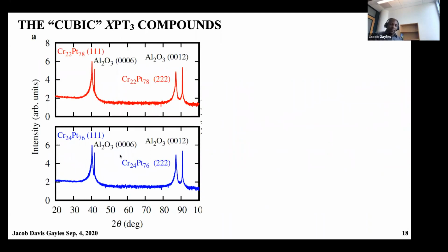And for the experimental part, we grew these chromium platinum materials. Here we distinguished the two different films of chromium by these indices, which are not completely accurate because there's about a 2% error in the EDX measurements of these films. We grew them on top of MgO, and capped it with aluminum oxide. It's about 60 nanometers thick. We grew it so that the normal to the 111 is out of plane, so that the three lattice vectors have an equal strain on them, so it keeps the cubic nature.